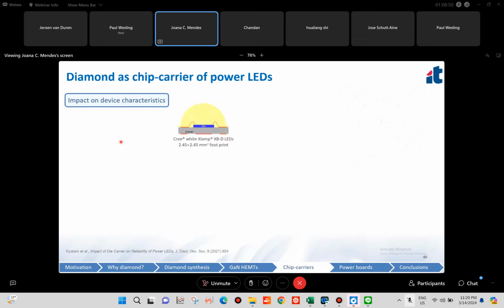And so we chose as a proof of concept these Cree white Xlamp XB-D LEDs. They have a very small footprint, 2.45 times 2.45, and they have an aluminum nitride carrier. And the thermal conductivity is somewhere between 60 to 193 watt per meter Kelvin, because these are the values reported in the literature. And we evaluated what would happen if we replace this aluminum nitride carrier with single crystal diamond with high thermal conductivity, and also with polycrystalline diamond with 1800 watt per meter Kelvin thermal conductivity.